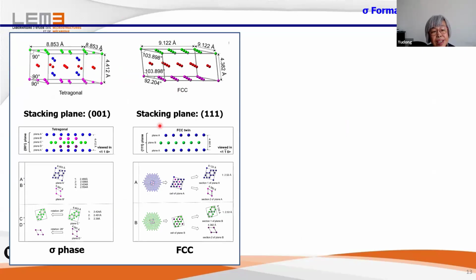We use the stacking of the 001 plane for the sigma phase, and for the FCC phase, we use this 111 plane, but we use 3 planes with a stacking fault here. Okay, and then we constructed the unit cell with these 111 stackings for the FCC phase and with 001 stacking of the sigma phase. We see the similarity between these two structures.